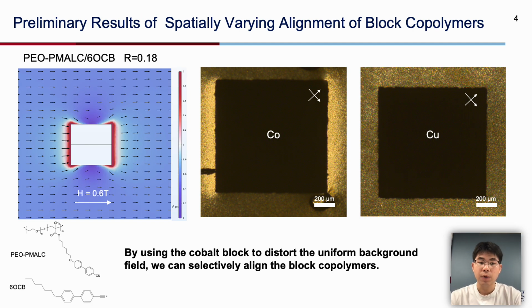So my research focuses on spatially varying alignment of block copolymers, and we start with a single cobalt block. The block polymer used is PEO-PMALC, which is a block polymer with a liquid crystal component side chain. We blended it with 6OCB, which is a commercial liquid crystal, to reduce the critical field needed for alignment, with a molar ratio R equal to 0.18.